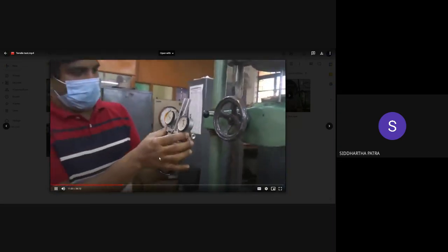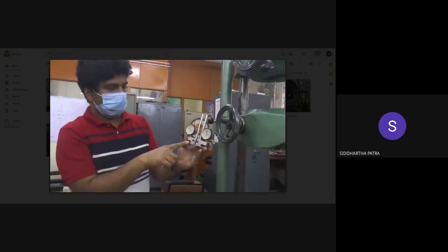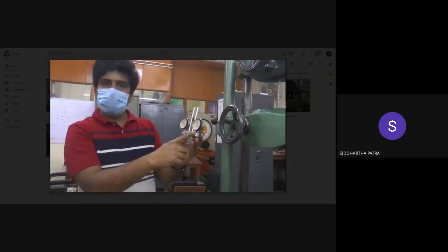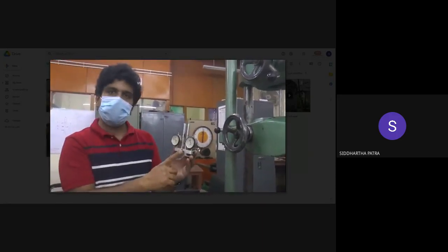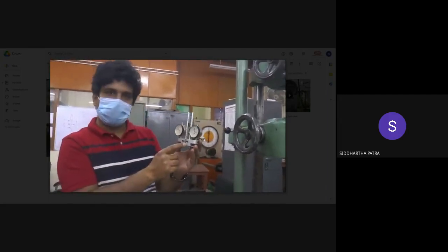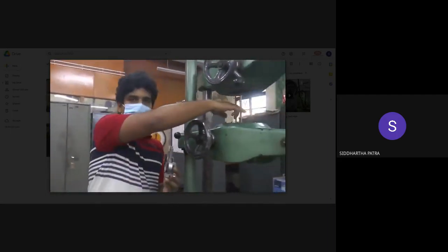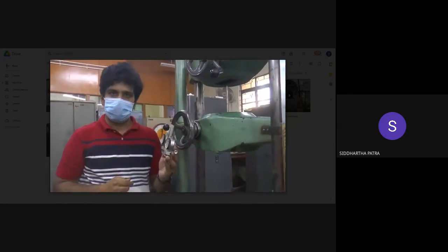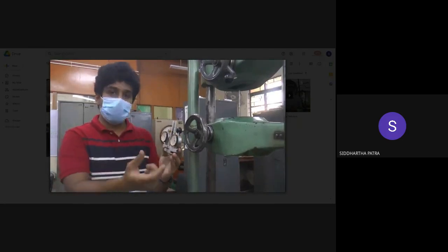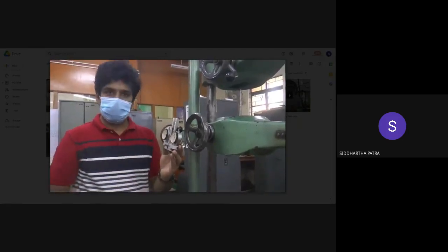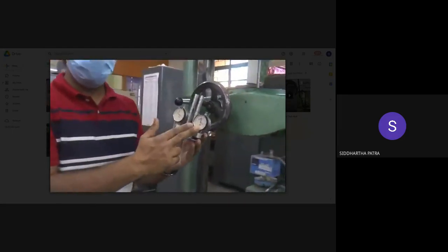So why do we need two dials over here? The thing is, it's a possibility that even with the extensometer attached to the bar, one of the knife edges might lose contact, might be in contact but not in static friction with the bar itself. Some slip may occur, and because of that slip, one of the dials, and we do not know which one, would not probably give you the correct result. Of course there is a chance of both of them not giving you the correct result.